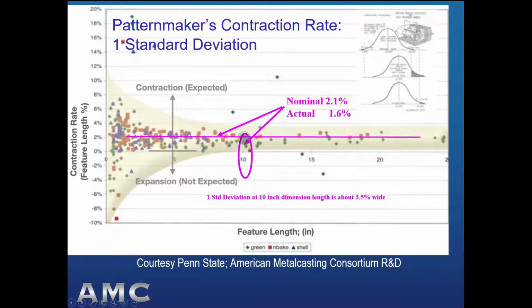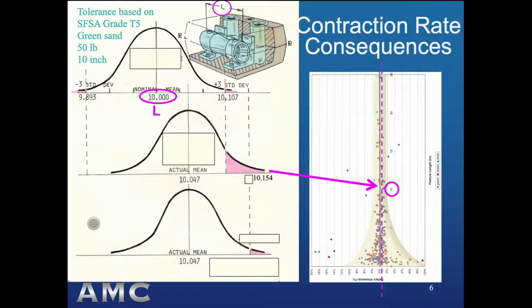So you can see that even as a longer dimension where the one standard deviation gets smaller, we still have significant variation. The consequence of this wide variation in pattern maker's contraction rate is difficulty in centering dimensions within their specified tolerance range. Here we have a 10-inch dimension, and the tooling was built for this casting, and we used an expected 2.1 pattern maker's contraction rate, but only got that 1.6% rate that I highlighted on the prior slide. So our process is capable of meeting the dimensional tolerance band specified, but our center of the dimension is off by the amount of the error in pattern maker's contraction estimate.